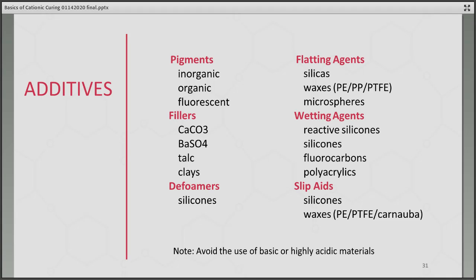One thing to note, and definitely remember, avoid using basic or highly acidic materials as additives. And when you think about it, it makes sense. Basic materials would tend to quench the acid that's generated to start your reaction. So you're pretty much dead before your polymerization starts. And highly acidic materials may actually kick off your photopolymerization before you wanted to. So you avoid basic and highly acidic materials, and you'd be fine.